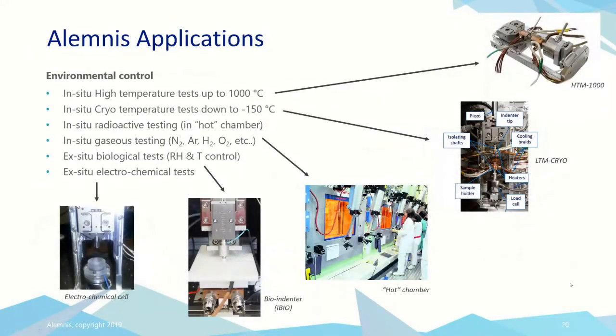Just something about environmental control. You can see up here the high temperature module mounted on our platform. So this allows you to get up to 1,000 degrees Celsius. We have a cryo module for getting down to about -150 degrees C. We have quite a few systems in nuclear radioactive chambers for looking at different levels of radioactivity in materials.